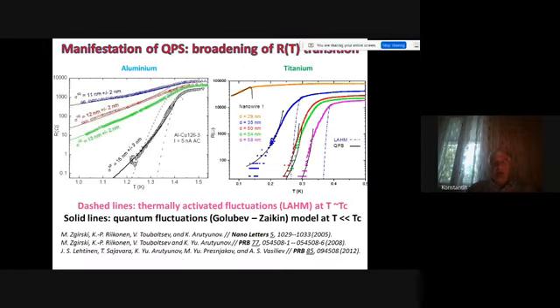Is this observable? I would say like this: if the cross-section is larger than the coherence length, we are no longer in the one-dimensional limit. So there might be parallel channels of current and the physics is completely different. But the interesting thing is that we can be at the limit between standard thermodynamic fluctuations and quantum fluctuations. For example, on the left image, the thermodynamic fluctuations are shown with dotted lines and solid lines are shown for quantum fluctuations. So for sufficiently thick nanowires, but still one-dimensional, you can observe standard thermodynamic fluctuations. And for very narrow ones, quantum fluctuations start to dominate.